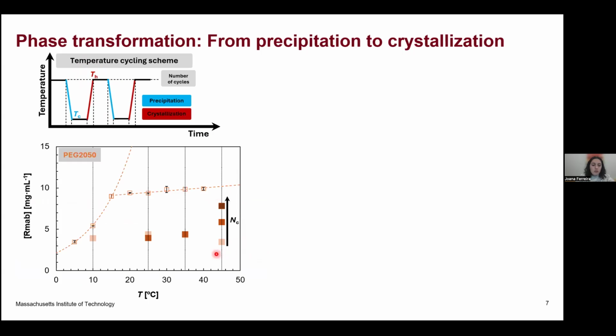We could also see the impact on the phase diagram. By increasing the number of cycles, we are close to reaching the solubility limit. Something that I also want to point out is that this has been reported for more complex proteins, and it is something that we also observe for this specific map: you can basically divide the phase diagram, the solubility limit, into different regions.